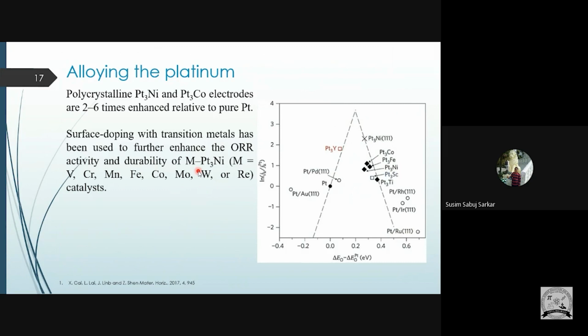That means platinum may be washed out by the electrolyte, because the electrolyte has a very high pH, since we are using 6 molar KOH, as we told, in the case of a zinc air battery. So we have to make the catalyst durable.